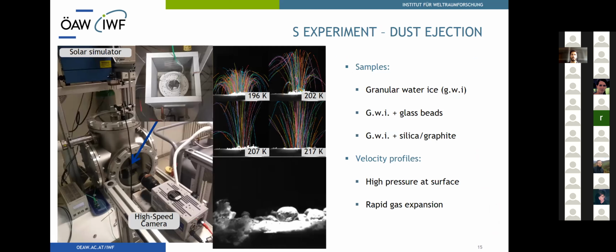With the same measurement setup, another experiment regarding cometary activity was performed. The process analyzed here was the ejection of particles due to gas pressure from sublimation. The primary target of this investigation was to develop a method to track the ejected particles in future experiments. After a successful implementation, the computed acceleration and velocity profiles indicated that a high-pressure environment can form directly at the sample surface, which could probably develop due to rapid gas expansion. In this video, you can see how a large chunk of dust moves as material is ejected from the surface around it.